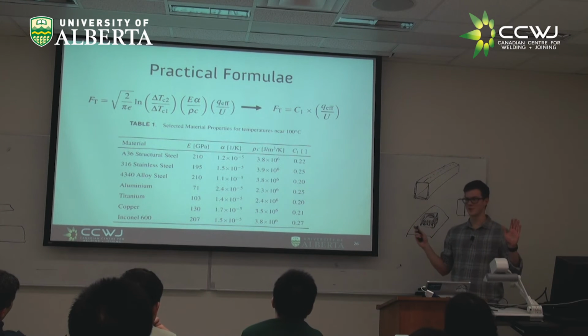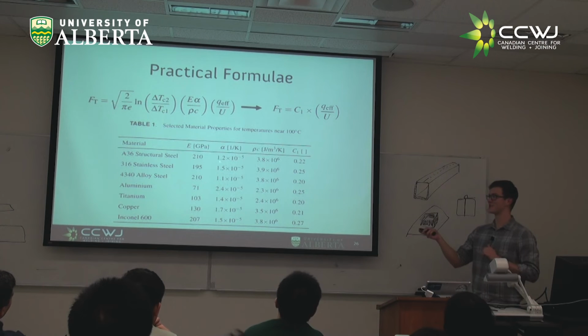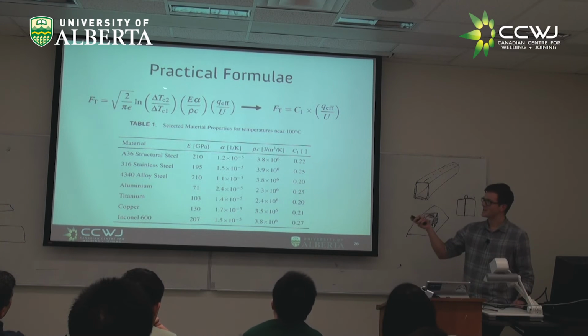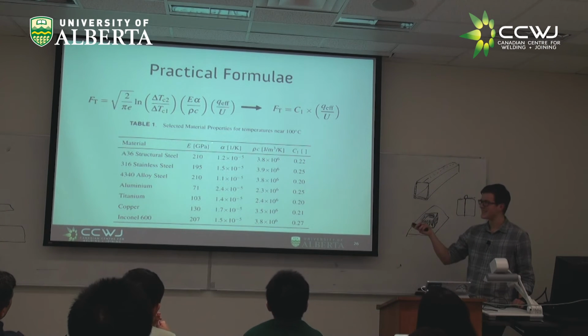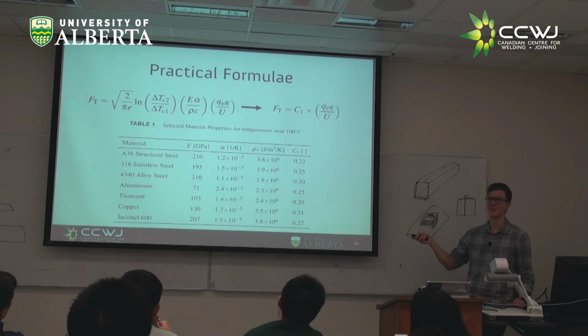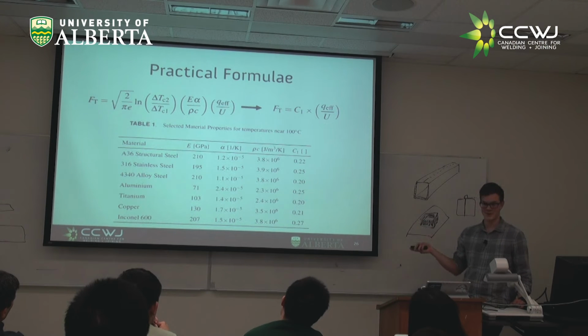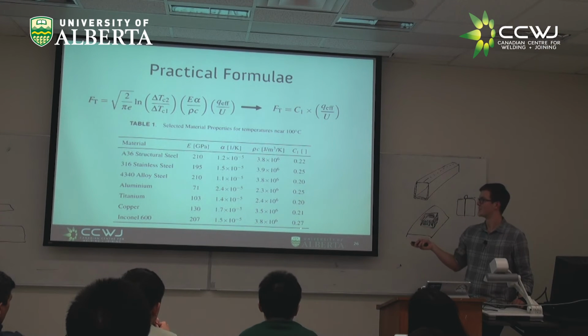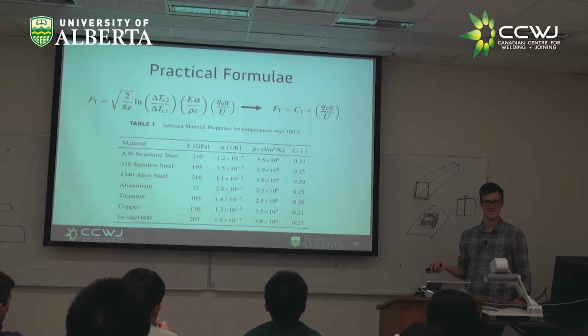Now, there's a lot more chemistry and physics behind that relationship. This is just a rule of thumb. But if you understand it, you shouldn't be surprised that as this is higher or this is lower for some materials, in general, alpha is a little bit higher. And where this is higher, alpha is a little bit lower. So although we get a factor of 3 difference here and a factor of 2 difference here, we're not seeing a factor of 6 in our coefficient. We're really seeing maybe a 50% change all the way from alloy steel up to Inconel.